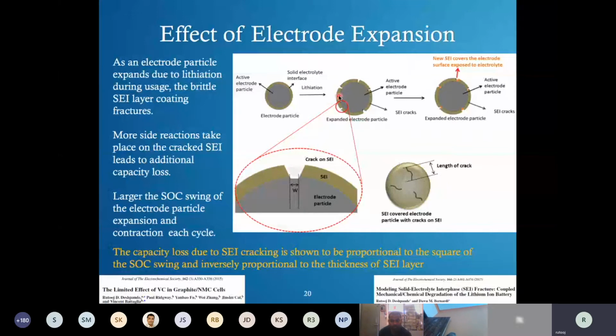So as soon as the coating layer breaks, there is much more electrode surface exposed to the electrolyte. So electrolyte basically seeps in through all these cracks and performs more side reactions. So there are more side reactions happening on these exposed surfaces, and this will result in more capacity loss. That's why we typically see more capacity loss when we are cycling than when we are storing it, even if we are cycling at low rates. So this is just an expansion-contraction effect.